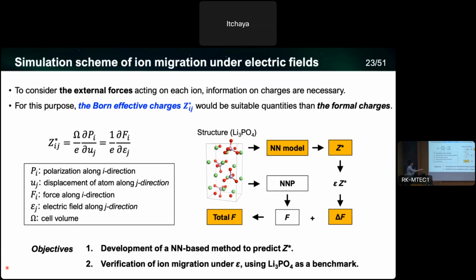So for given structures, we first construct the neural network potential used as the force field. And we prepare another neural network model to predict Born effective charge. And we can multiply the uniform electric field times Born effective charge to get the external forces. And sum of them are considered as total forces. And from these total forces, we can do the dynamical calculations.